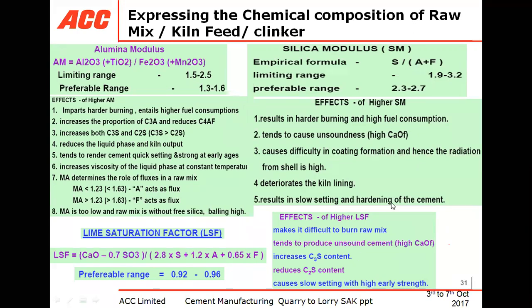And if you have high LSF, if the lime saturation factor in the raw material is high, then it makes it difficult to burn the raw mix. It tends to produce unsound cement, increases C3S and reduces C2S. That means increased C3S gives you good early strength, but you will not get good later strength, because C3S is responsible for early strength. It reduces C2S content if you keep a high percentage of LSF.